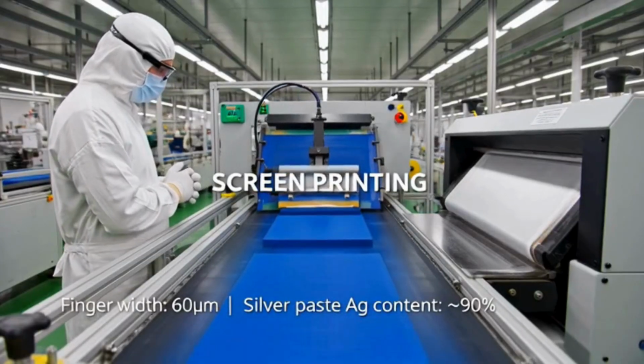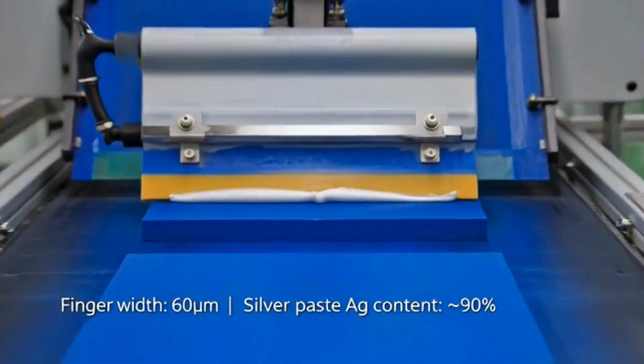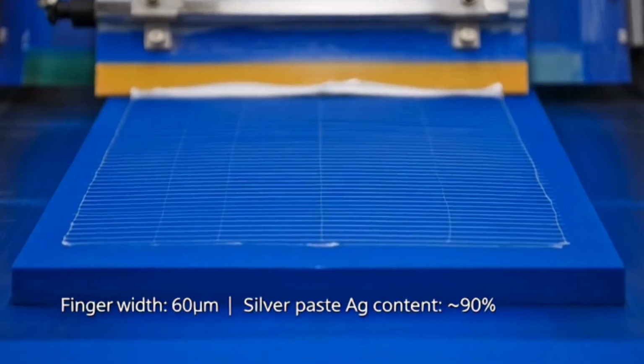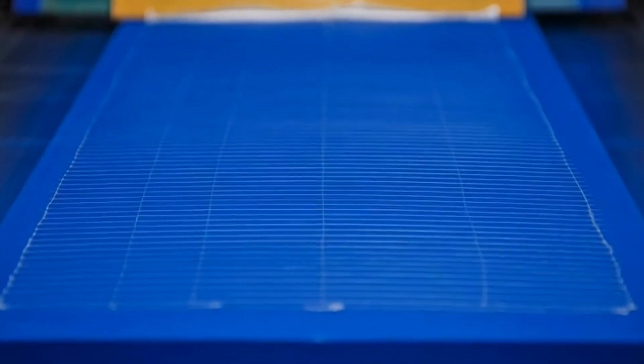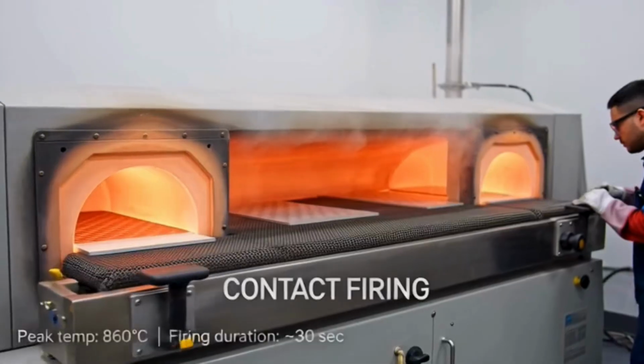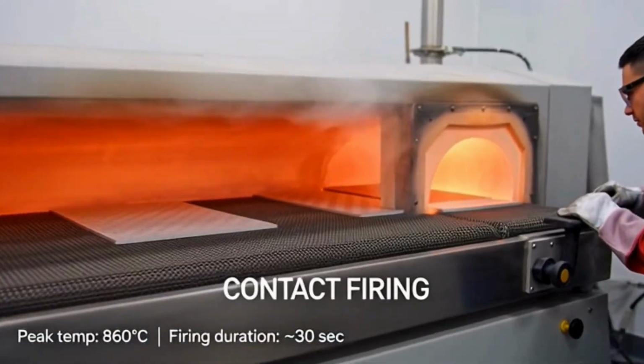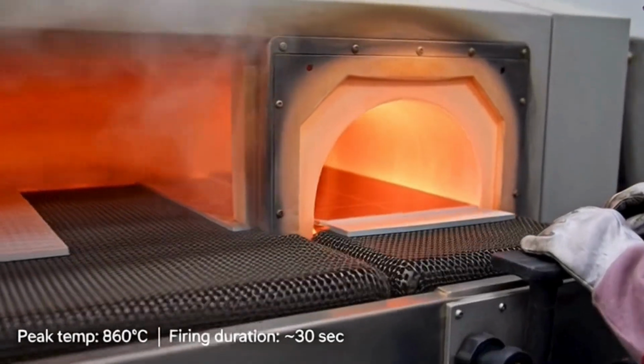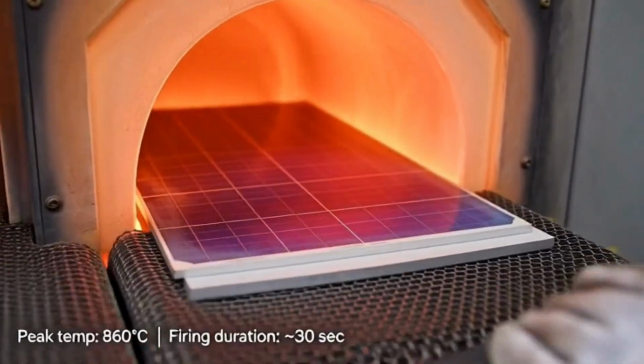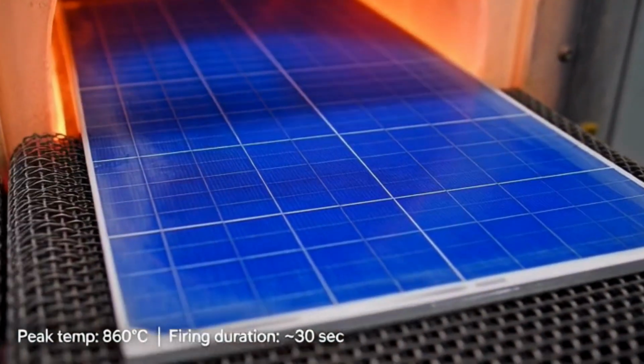Silver paste is pressed through a fine mesh stencil, printing electrical contacts directly onto the cell. These microscopic finger lines will carry current from the cell to the circuit. The wafers pass through an infrared firing furnace, peaking at 860 degrees Celsius. Silver contacts fuse permanently to the silicon. The cell is now electrically complete.